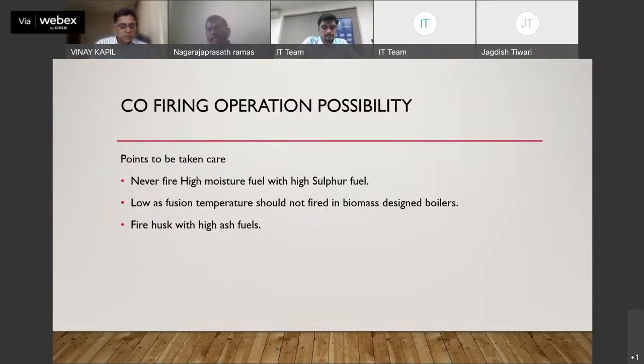And the possibility of co-firing of biomass with the fuel. What happens? Points to be taken care when we fire high moisture biomass like bagasse or high moisture husk. You need to consider that sulfur should not be there with the co-firing fuels. If sulfur is more, then there will be more possibility for corrosion in the downstream, like air preheater and economizer inlet water cold zone. There will be a possibility of more corrosion.